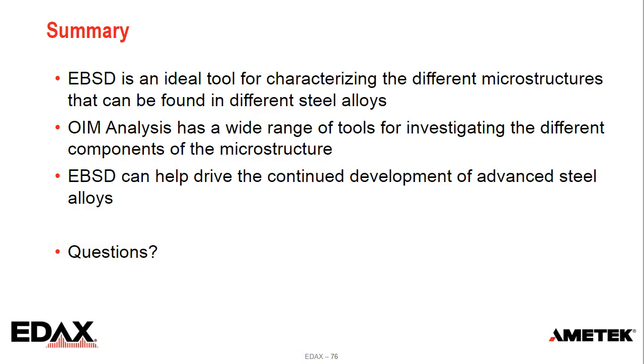The thing with EBSD to remember is we're a surface measurement technique. So when we prepare a surface, we're looking at a free surface, and that can also cause some possible relaxation and transformation, whereas XRD will look at a volume. So when you're comparing measurements from different techniques, it's important to know how they work and how they sample and what the effects can be, because you very rarely get a perfect one-to-one comparison.